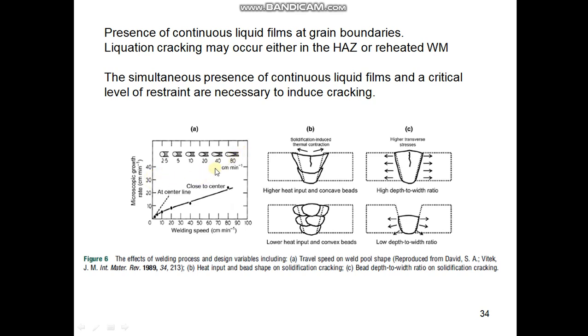the weld center line. In the second figure, you will see the heat input and the effect of bead shape. In this schematic B, because of this larger bead shape, due to the thermal contraction during the solidification process, the solidification induces weld center cracking. In the lower figure you will see a lower heat input with convex beads. You will see there are a number of beads. With a number of beads and a lower heat input, the heat will be distributed very finely, and you will not have a problem of solidification induced cracking, because through increasing the number of beads, the heat will be properly distributed from the arc.